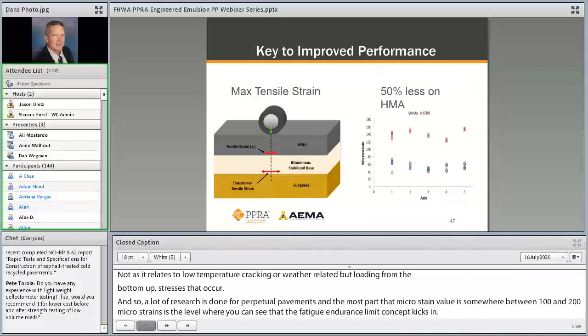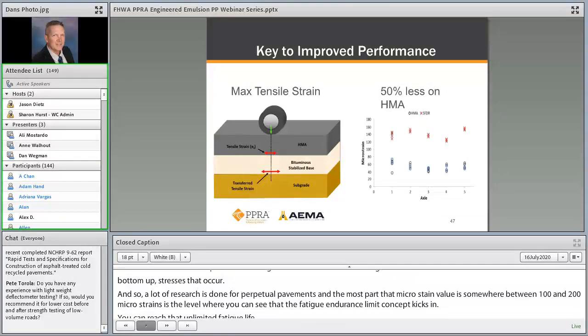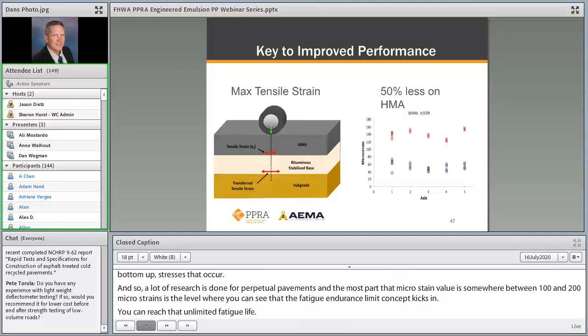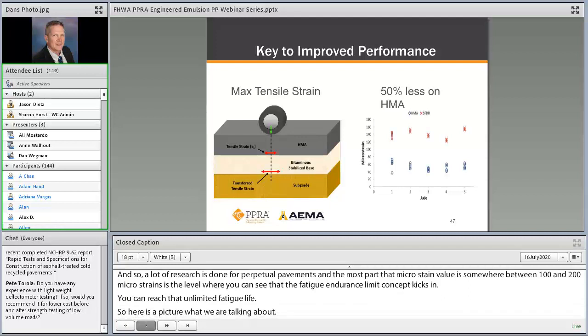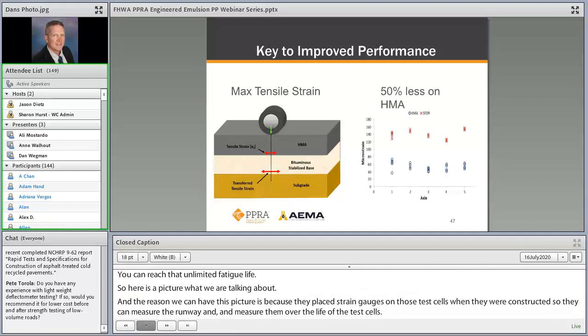So here's a picture of what we're talking about. The reason that we can have this picture is because they placed strain gauges out on those test cells when they were constructed. So they could actually measure the strains in the roadway and measure them over the life of the test cells. You can see there on the left, you've got the bitumen or the engineered emulsion stabilized base, and that maximum tensile strain has been transferred down to the bottom of that material because it's a bound material.